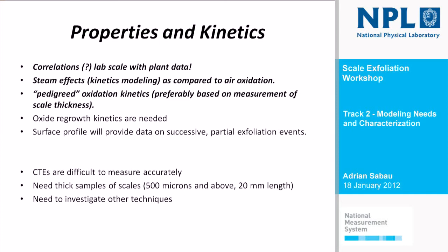At NPL here it was pointed out that coefficients of thermal expansion are very difficult to measure. There are limitations due to the instrument, limitations due to the sample preparation, and limitations due to just the nature of the oxide itself. Microcracks and defects affect the measurement.